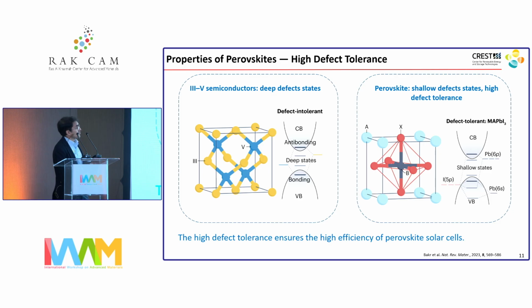But with perovskites, because both the conduction band and the valence band have anti-bonding components, when a defect forms, that defect is either shallow, close to the band edge, or in fact within the valence band. And so it's not really a stopper for charge carriers, but more of a speed bump, so to speak.